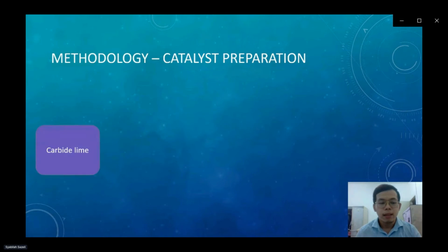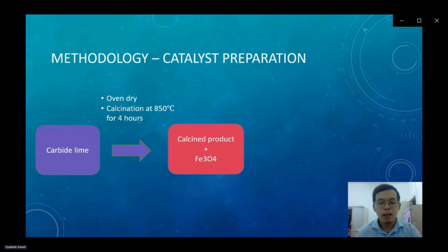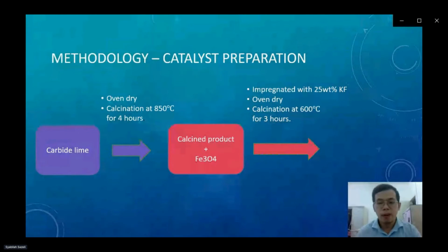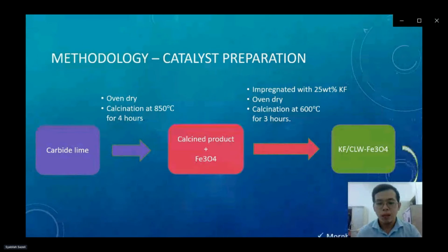Next, the carbide lime will be oven dried and calcined at 850 degrees Celsius for 4 hours. Then the calcined product will be mixed with the Fe3O4 produced previously and impregnated with 25% of KF, oven dried, and calcined at 600 degrees Celsius for 3 hours. And lastly, the KF/CLW/Fe3O4 will be produced, and it will undergo morphology analysis, structure analysis, base strength analysis, and elemental analysis.